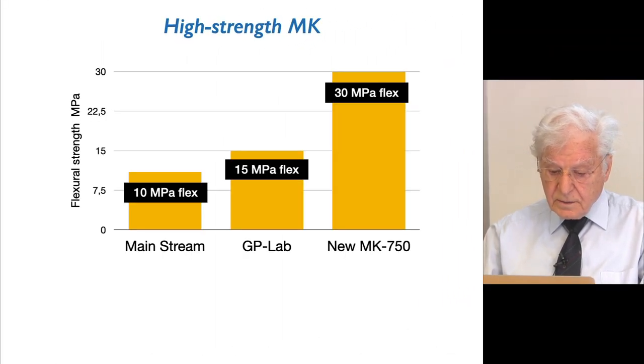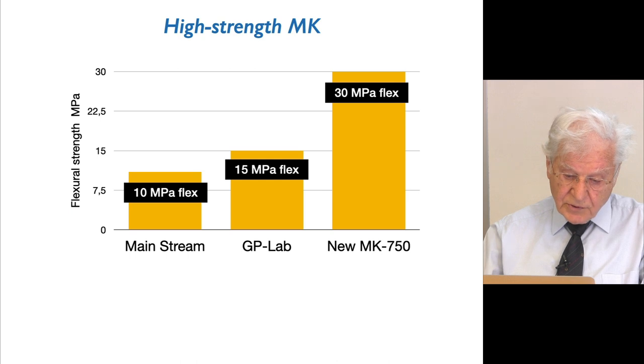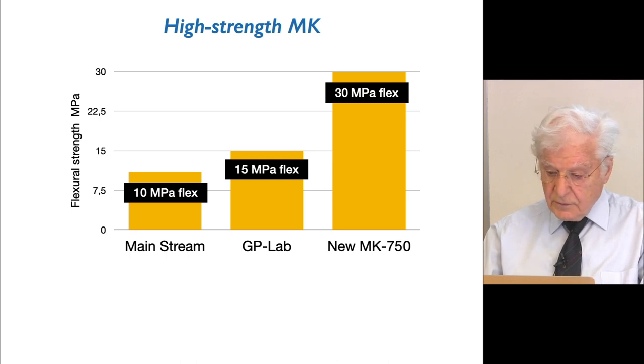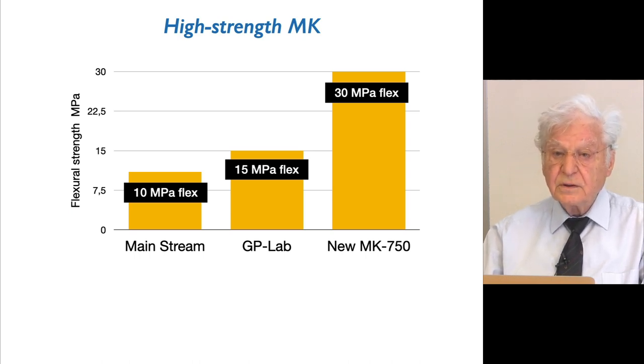In the literature, here we have the flexural strength, the mainstream flexural strength is around 10 MPa. For all purpose commercial metakaolin, we have in our lab 15 MPa. And the new metakaolin have a flexural strength of 30 MPa.